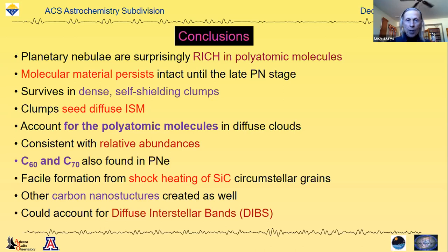We know that the most complex molecules found in planetary nebulae are fullerenes. And we believe we found another possible formation mechanism for the synthesis of C60 and C70 and possibly other nanostructures from the shock heating of silicon carbide circumstellar grains. And shock heating basically evaporates the silicon and the carbon just naturally forms graphite. And then you also get the formation of the 5-membered rings necessary for C60. Other carbon nanostructures are probably created as well.